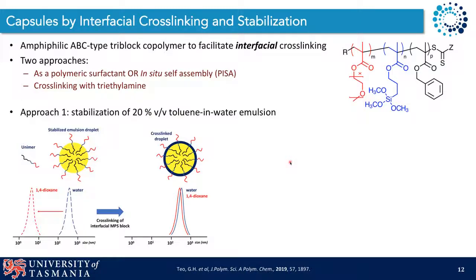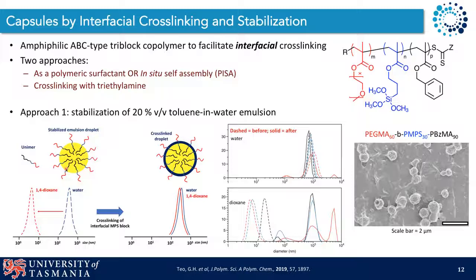We also wanted to investigate whether we can form capsules by an interfacial cross-linking and stabilisation method. The approach that we used was to use triblock copolymers with a PEG methacrylate block as the corona, the MPS block as the interfacial region, and benzyl methacrylate as the core forming block. We used these triblocks to stabilise oil in water emulsion droplets, and then cross-link that interface through the addition of a water-soluble base. We could indeed demonstrate that principle.